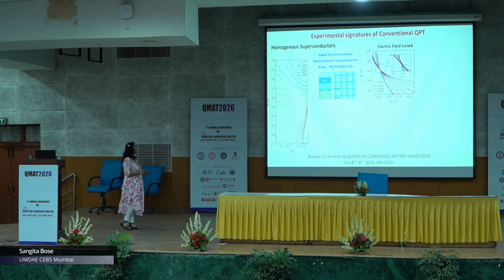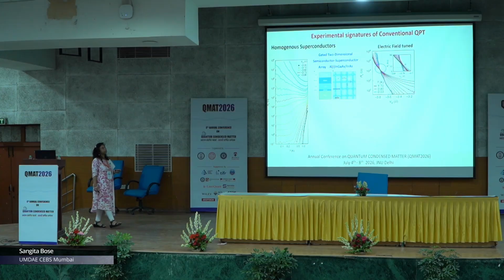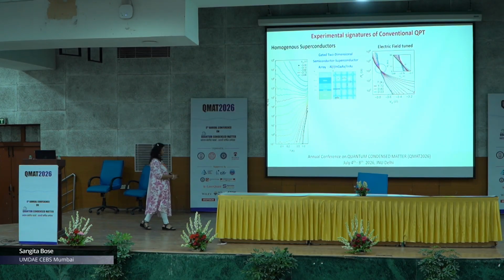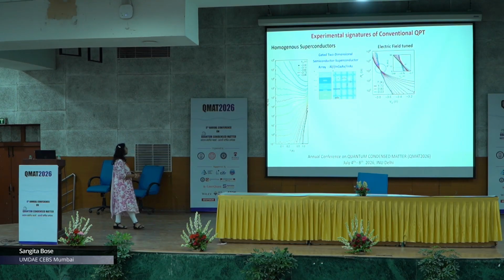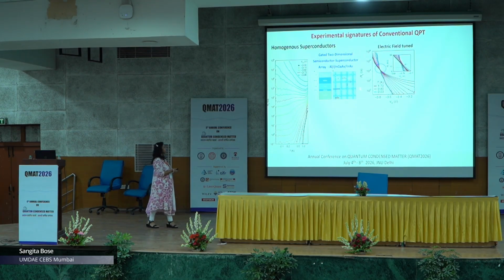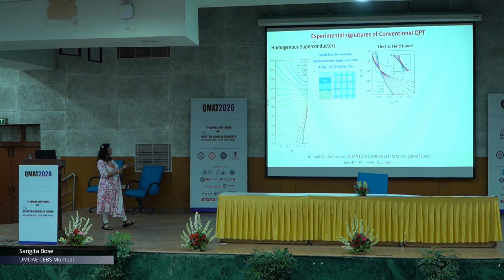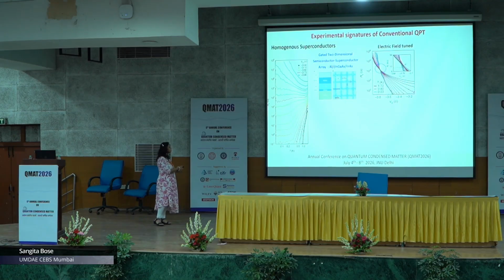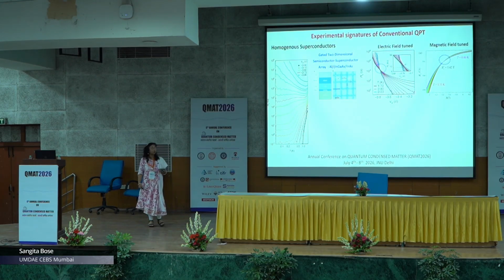When you come to homogeneous superconductors, what are the experimental signatures for a conventional quantum phase transition? This is an experiment done in a gated two-dimensional semiconductor-superconductor array. By tuning the gate voltage, you can go from the superconductor to the insulating transition. If you look at the magnetoresistance isotherms, you see that they all cross at a single point. This is the quantum critical point where the system goes from the disordered to the ordered to the disordered phase.